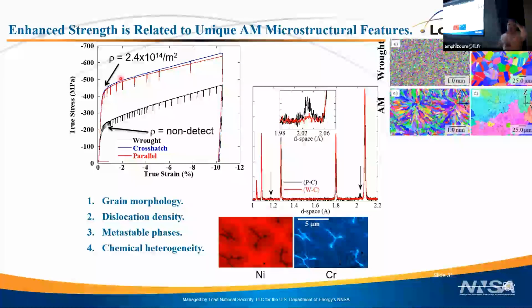So we devised a set of experiments where we heat treated the material in situ. An industrial process, right? We heat treat it, we anneal it, and we're going to watch each of these things change in the microstructure. And then we're going to test the material again and try to relate which part of the microstructure we pull out to the amount of strength that remains in the material.